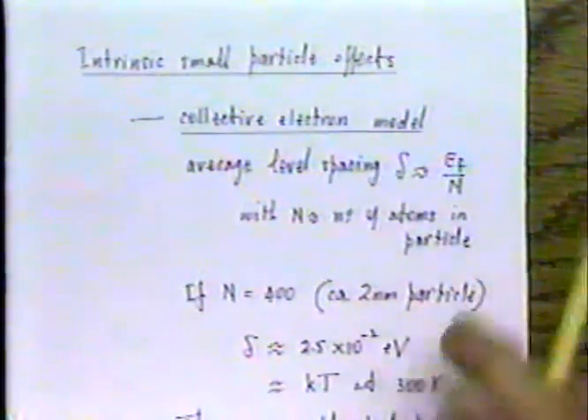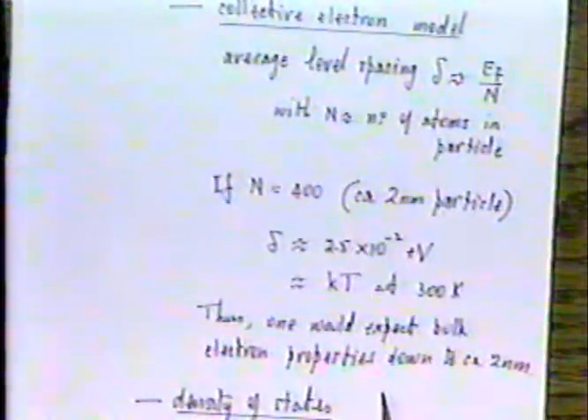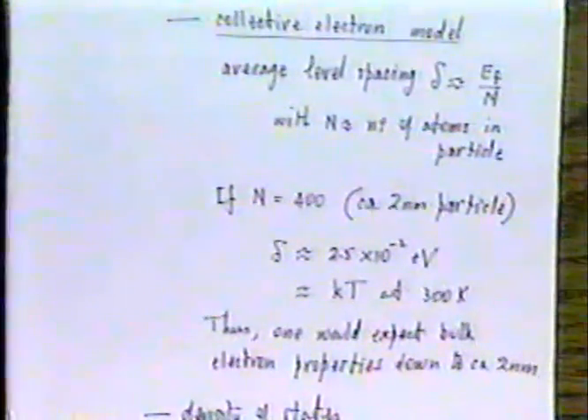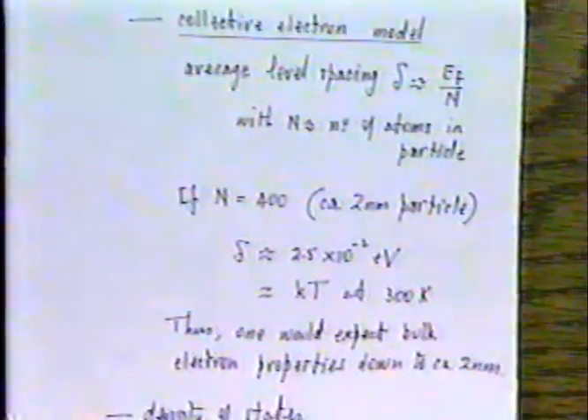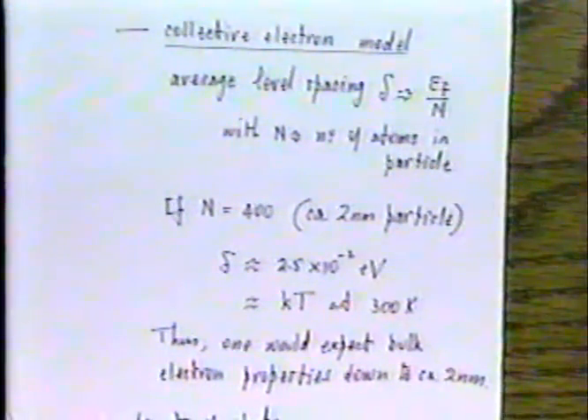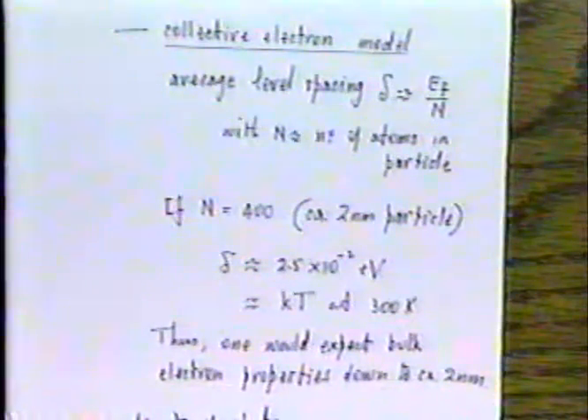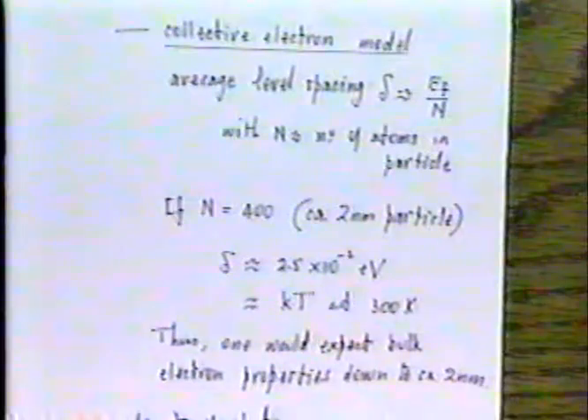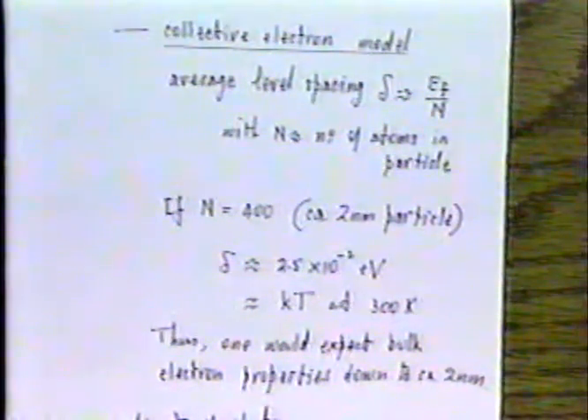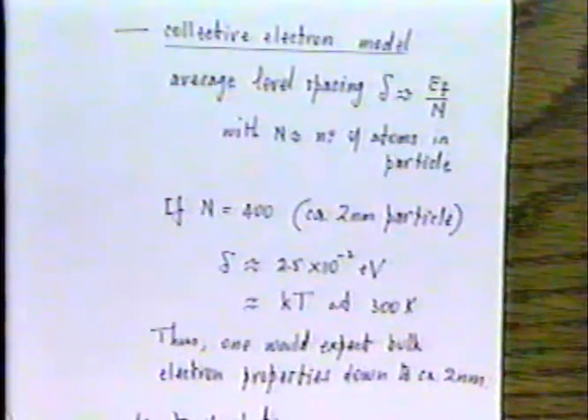So the simplest way to approach the question of how small does a metallic particle have to become before it has electronic properties differing from those of the bulk metal is to simply say, how many atoms can you have which will make the average level spacing roughly the same as the thermal energy at the temperature at which you're going to make the measurement.